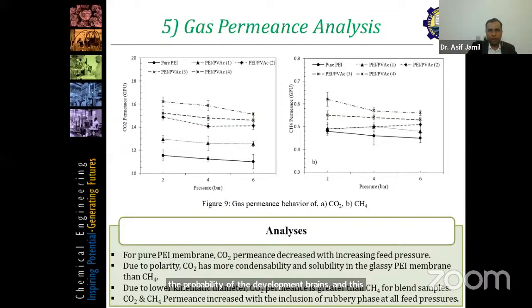these structures were expected. But fortunately, we have no cracks or defects in the system. And the finger-like pores increase the permeability of the developed membranes, and this will be reflected in the gas permeation analysis.